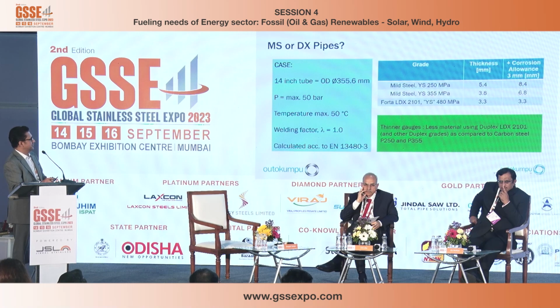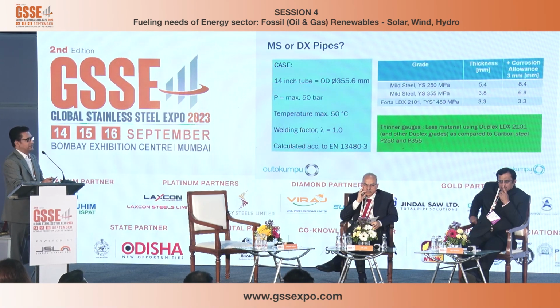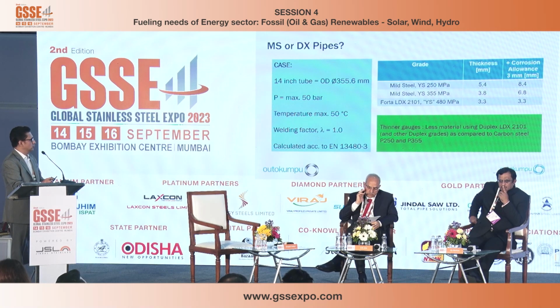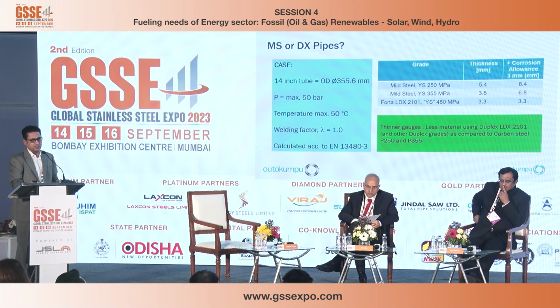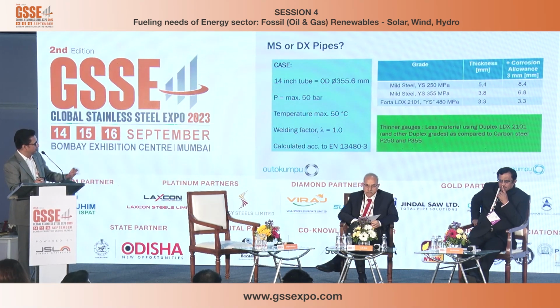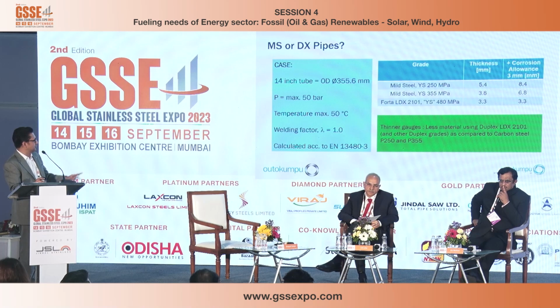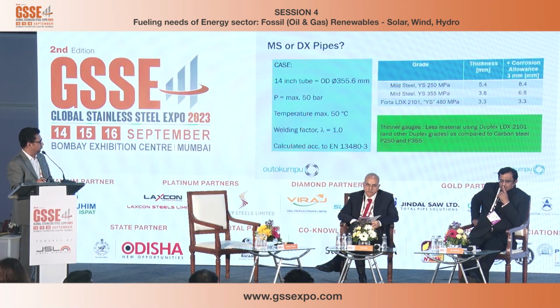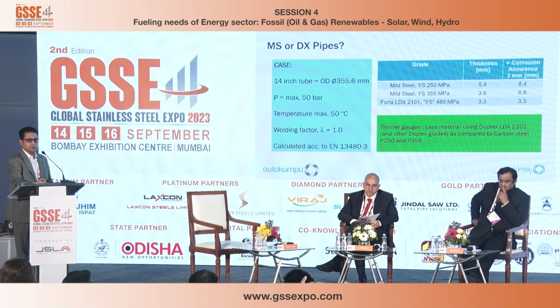And here what we have taken is mild steel, 250 megapascal strength, another is 355 megapascal strength, and we have taken lean duplex LDX 2101 with the yield strength of 480 megapascal. And when you use the carbon steel, normally they are adding 3 mm of corrosion margin into that. So the worked out design thickness according to this standard for that pipe, for these conditions, is 5.4 mm, 3.8 mm and 3.3 mm.